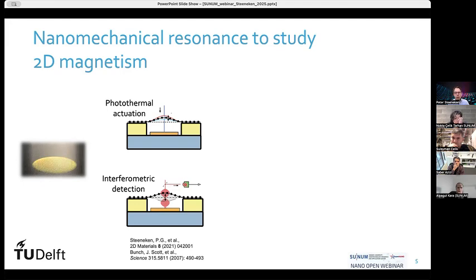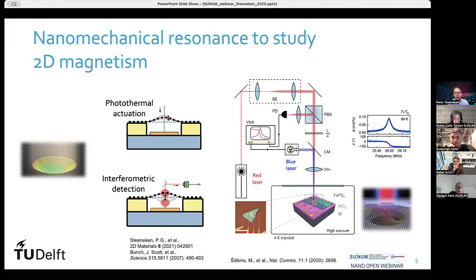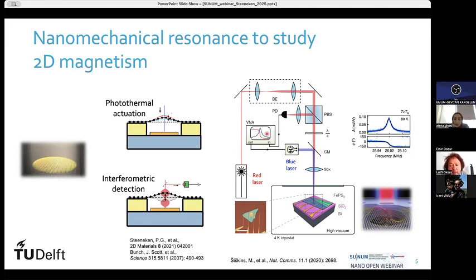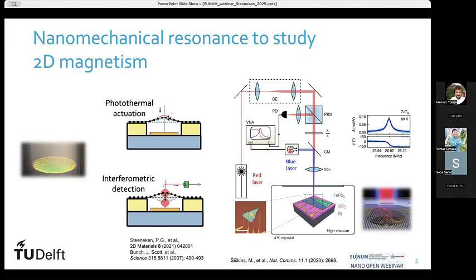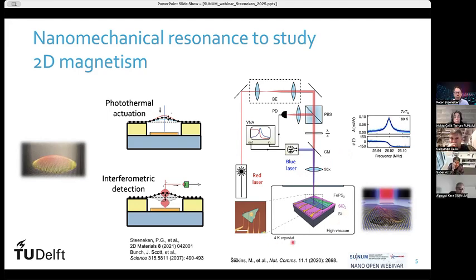We use a setup to have both the blue and the red lasers hitting our membrane, which has a diameter of about 5 micrometers and a thickness of a few nanometers. We separate them with a special filter. Then we use a network analyzer to generate the modulation of the blue laser and to detect with a photodiode the intensity variations of the red laser. When we change the frequency of the blue laser, we see that at a certain frequency, in this case 26 megahertz, we get a resonance peak. So we know that the membrane is in resonance at this particular frequency. This whole setup is in a cryostat, which can be cooled down to 4 Kelvin in high vacuum. So we can track this resonance frequency as a function of temperature.